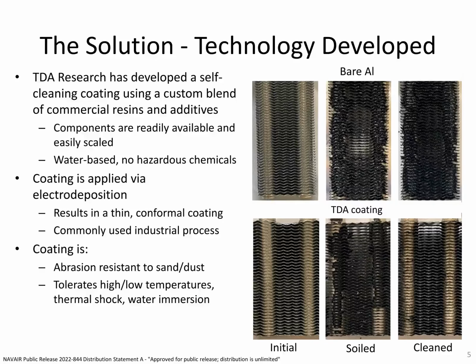The solution. TDA Research has developed a self-cleaning coating that uses a custom blend of commercial resins and additives. Rather than developing and synthesizing our own resin, we chose to use commercial components and optimize the additive blends to confer the desired functionality. We decided to go this route because we really wanted to provide a solution that could easily be scaled up for commercial applications. Our coating system is water-based and does not include hazardous chemicals or solvents.